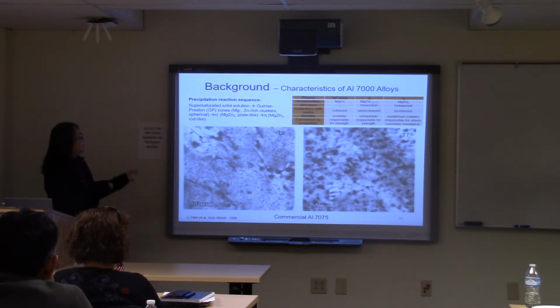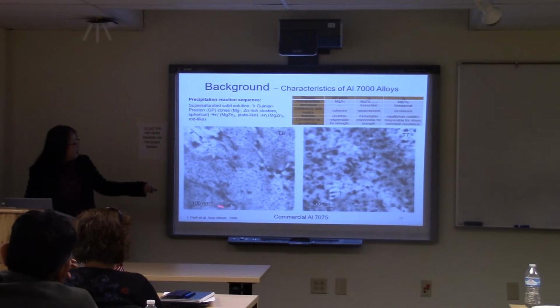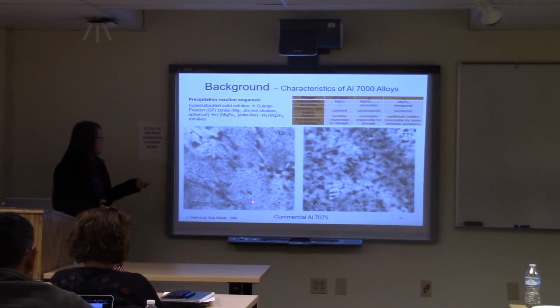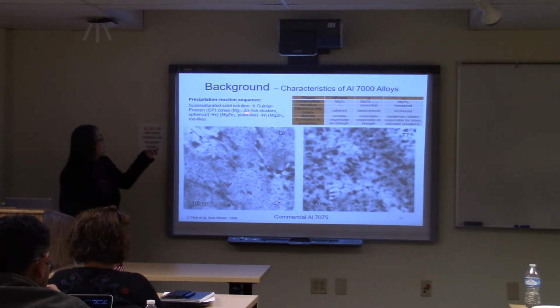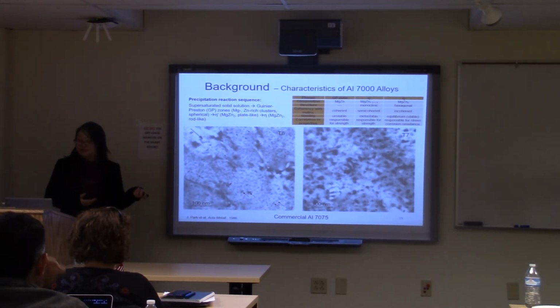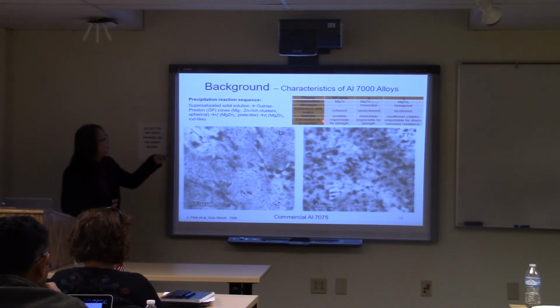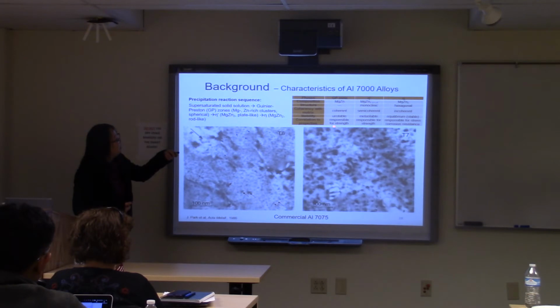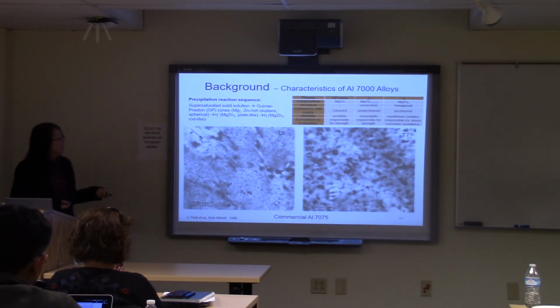After that, you start to heat up the material. Then the magnesium and zinc don't like the state because now the energy becomes higher, so they will creep out, which we call the GP zones. And this is a very old paper, at the very beginning, of how they found this, and it's from a commercial 7075. As you continue to heat treat the material, you will find some needle-like crystals, which is the eta prime, magnesium zinc 2. And here I just provide a table summarizing what the morphology is like. More important, I would like to highlight the GP zones and the eta primes, because their morphology and size are responsible for the strength we get in this alloy system.